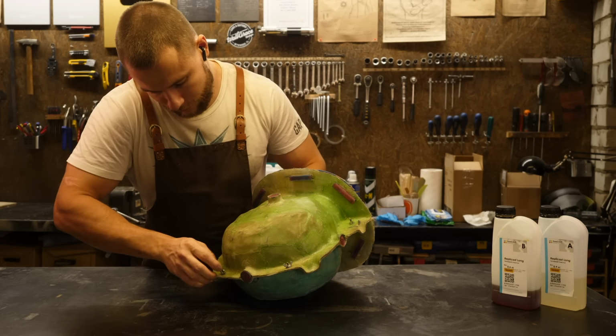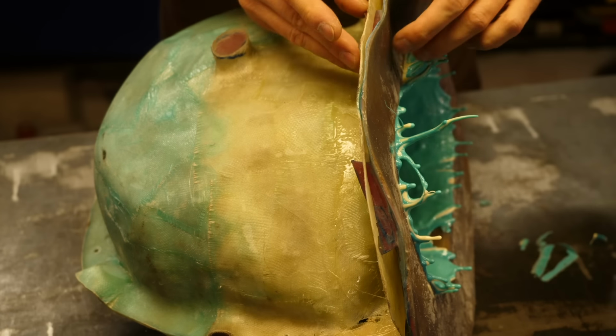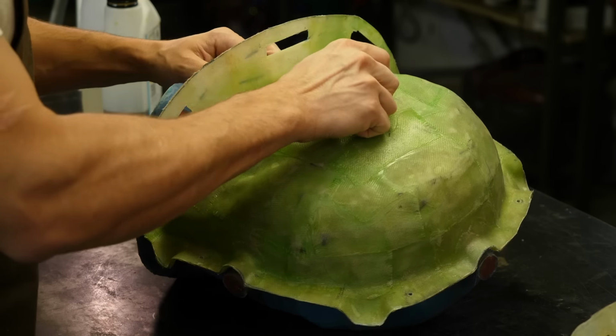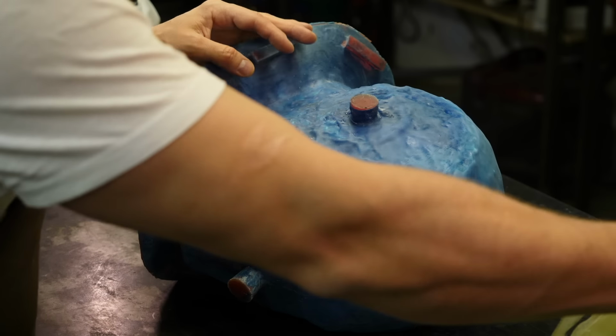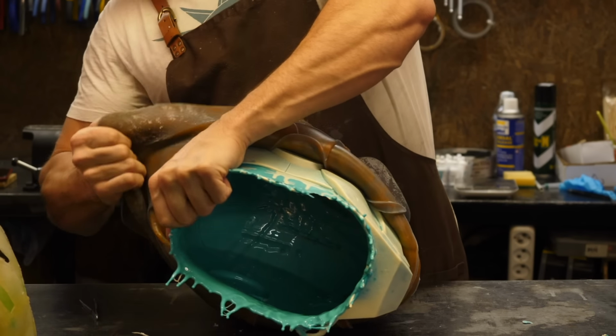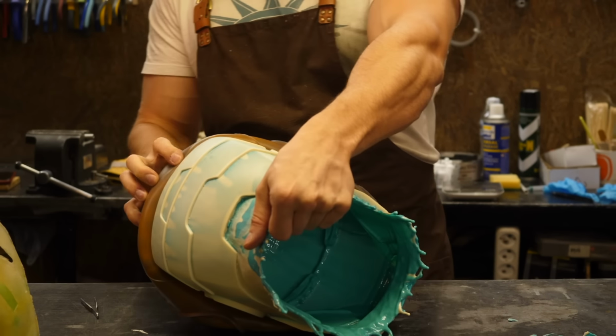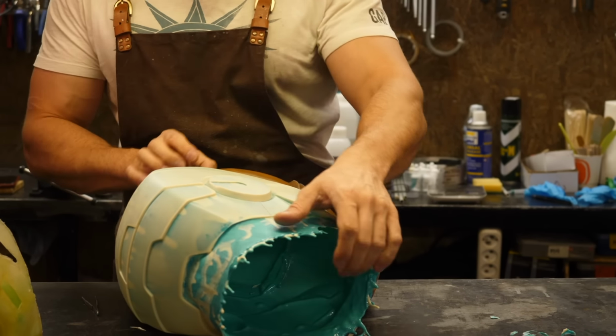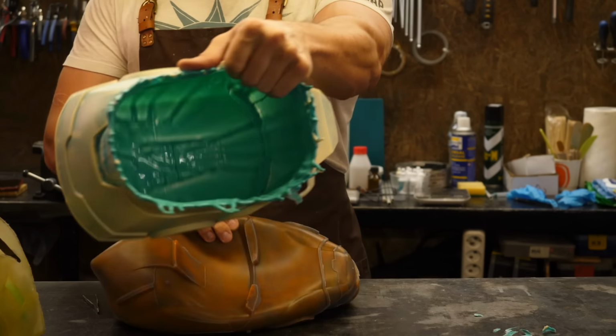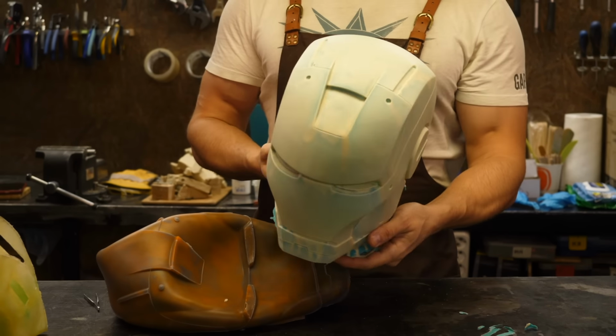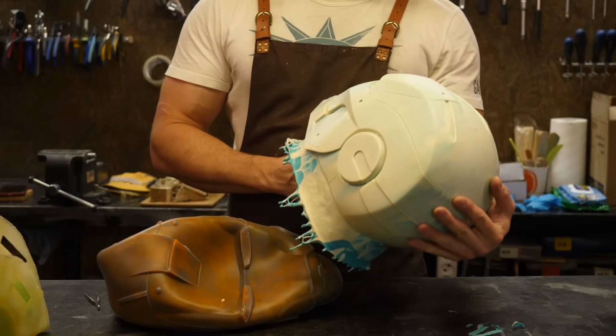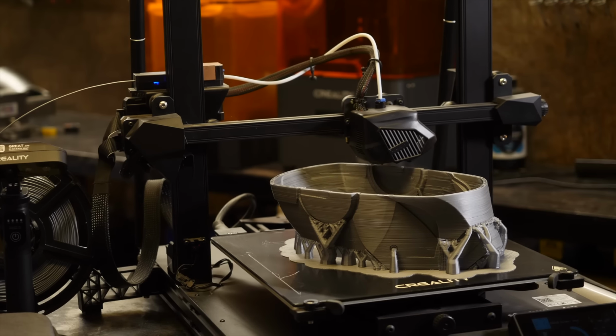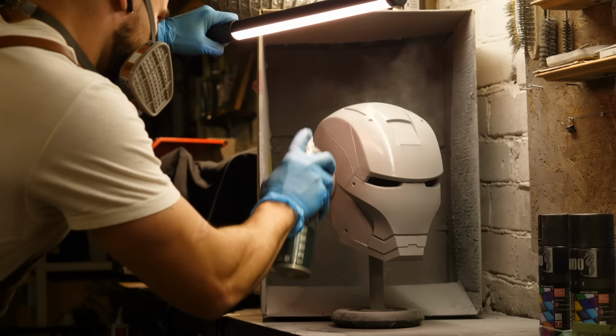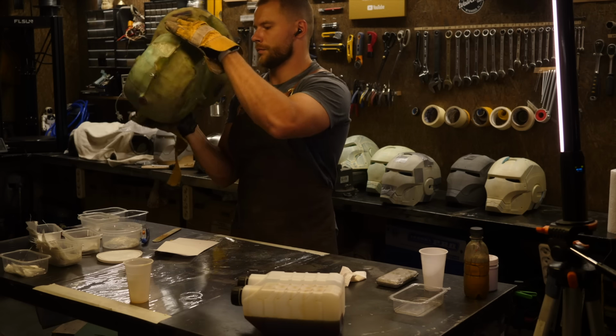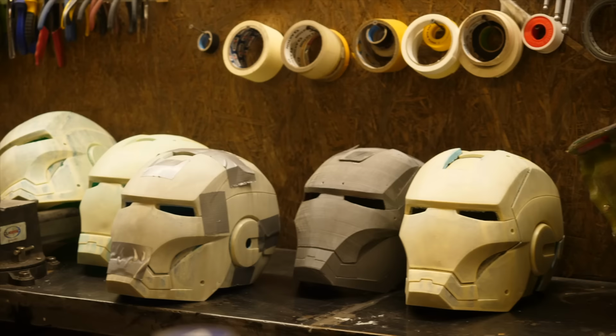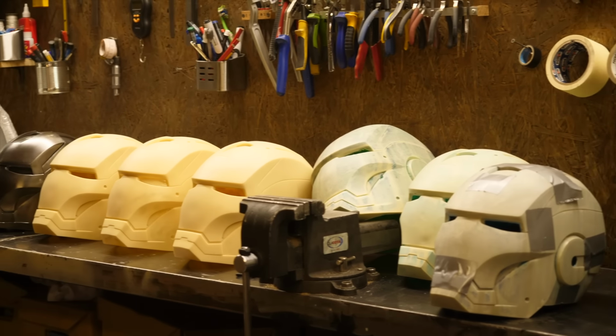A couple of hours after pouring the last layer, even without waiting for the final cure, the helmet can be removed from the mold and you can start making the second one, while the first one gains its final strength. Thus, if desired, in one working day you can make 3 or even 4 helmets with strength comparable to those 3D printed. Just imagine, to print and manually smooth one such helmet, you need at least 4 full working days. With casting, you can get 3 or 4 helmets in one day.